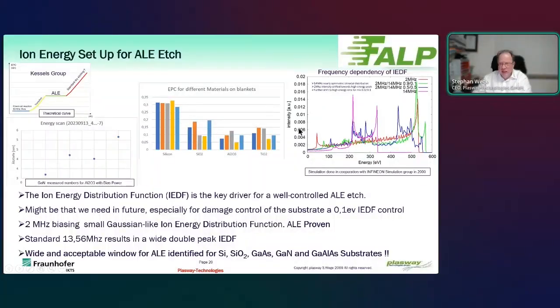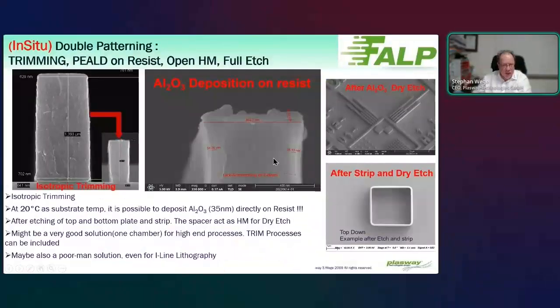And to do so, it is very important that you have a very good control of the ion energy. And we did it especially so that we have an independent control of plasma density and ion energy by the choice of the right frequency. So I don't want to go into this detail, but in principle, for this material, we have an ALE process available. What is nice for an ALE process is that you, on the one hand, can work with ion energy to create really atomic layer directional etching, but you can also work in an isotropic mode.